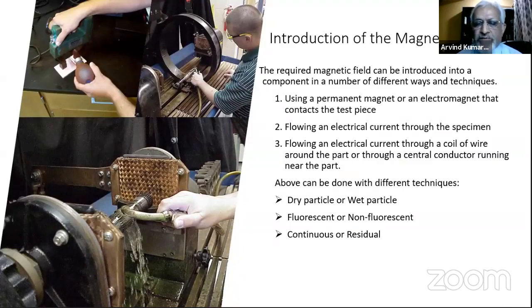Continuous method means that you are doing the interpretation while the magnetic field is on. You are magnetizing the part, you're not removing the magnetic field, and you apply the powders and see the indication being formed, and that is your interpretation. And after you have done that, then you remove the magnetic field. That is called a continuous method.